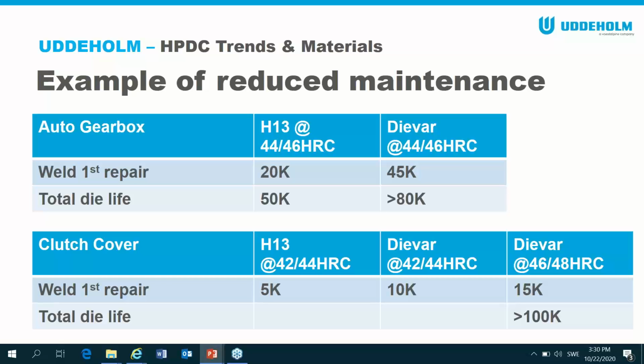In North America, here is a clutch cover example, a die which started in H13 at 42, 44 Rockwell. They get very different results. Obviously, the die is more challenging, so the life is less, but the performance increase is the same. It's a doubling. They get 5,000 shots with an H13 and have to weld repair. But with Dievar, at the same hardness, they get 10,000. Again, it completely shows the difference between Dievar and H13.